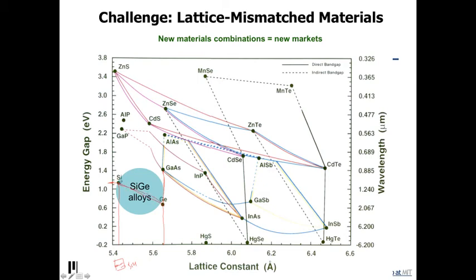So if you can figure out these alloys between silicon and germanium, so these would be the alloys in between, you can kind of use it to engineer different lattice constants across this. And if you could figure out how that all works, well, that would be the gateway to putting these materials on silicon and creating those integrated circuits, because you would have been able to get germanium on silicon of high quality. So the key thing is, can you span this and get high quality? Now it turns out that we were getting better results of germanium on silicon. We studied and learned how dislocations nucleate and propagate, and it gave us insight to my key invention, and then we were able to demonstrate that.